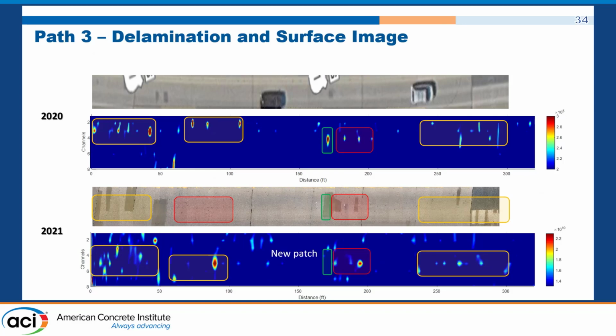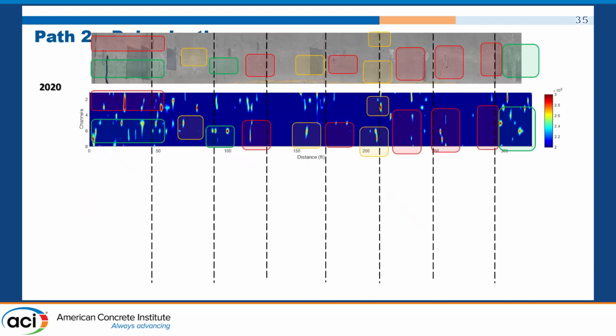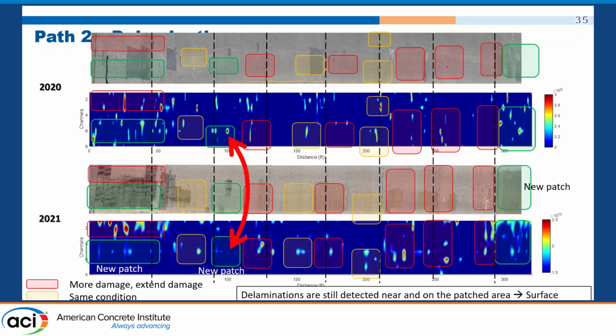But when you look at this one after the patch, you can see that the delamination is gone, over and over. We can see that we can verify the subcontract quality. But sometimes if you look at this, it's correctly matching here, but I'm talking about the green color. If you look at the red color, which is after the patch, the new repair is even growing actually.